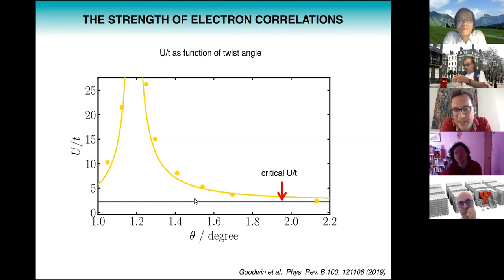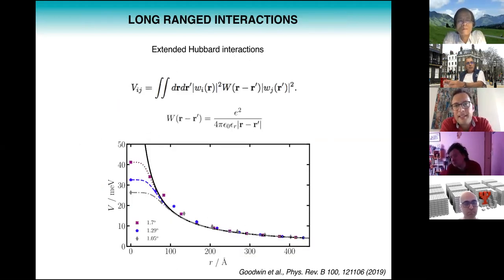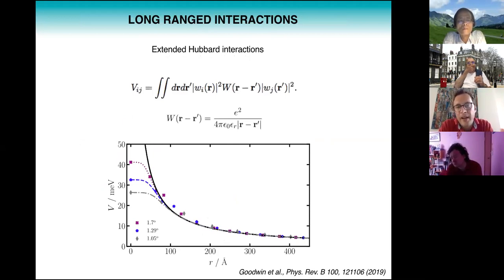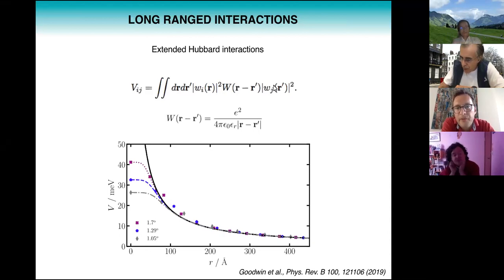So there must be something wrong, because this prediction is in disagreement with experiment. Obviously what's wrong is that we're dealing here with a two-dimensional semi-metal, and we know that these materials have long-range interactions. So what we can look at are extended Hubbard parameters. Here we're calculating the matrix element of the interaction between Wannier functions in different moiré unit cells. Here I'm showing you how these Hubbard parameters decay as a function of distance, and the black line is just the bare Coulomb interaction. I'm showing you results for 3 different twist angles, and after 100 angstrom or 10 nanometers, they all fall on just the 1/r line. So basically this tells you that you should really look at the long-range interactions. Just on-site Hubbard is not going to be good enough.